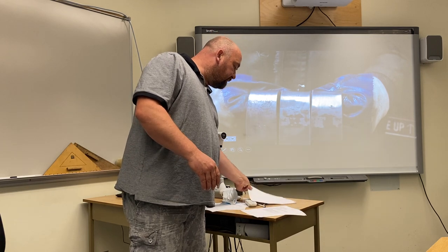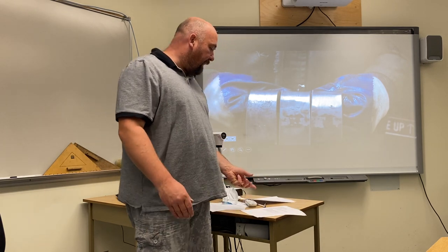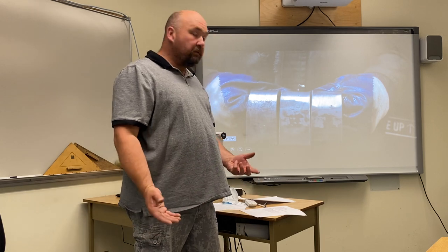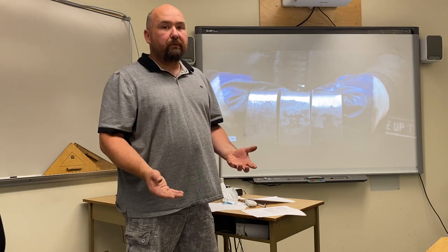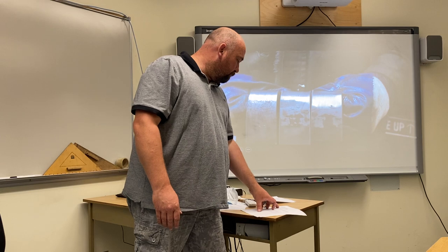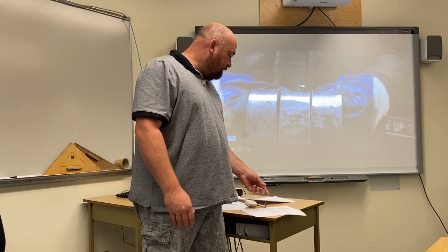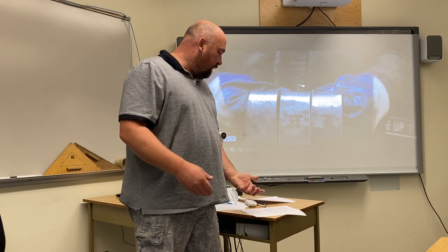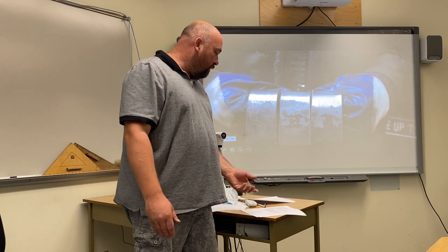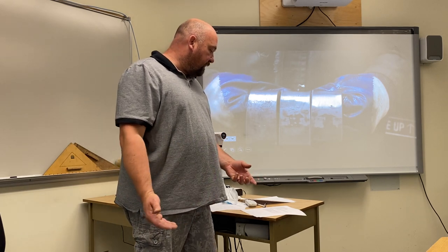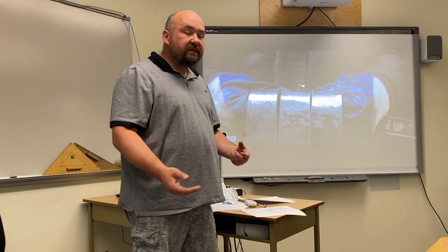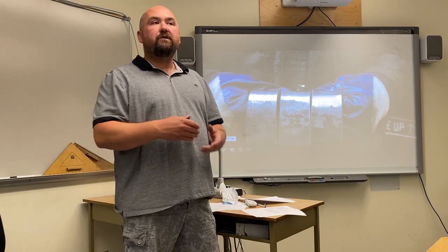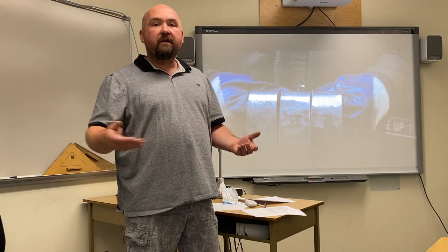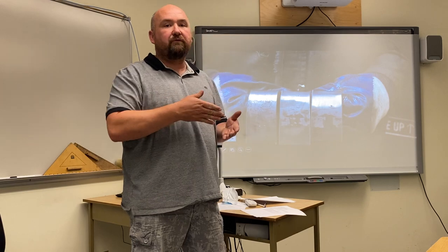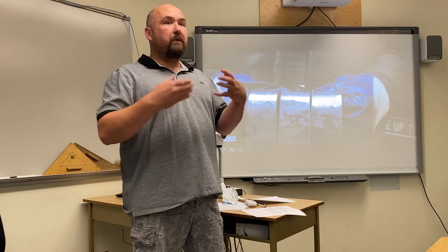So now, the variations. The most common types of failure are lack of fusion at the root of the fillet weld side. That's the most common type of failure. Causes are insufficient heat, poor manipulation or technique, and an incorrect electrode angle. Incomplete fusion or slag inclusion at the restart is another common thing. You don't let your arc reestablish well enough before you come back, and then you let the puddle get in front of your weld, like we've talked about while you guys are going through all of your practicals that you have been.